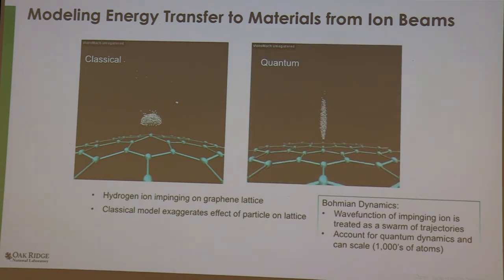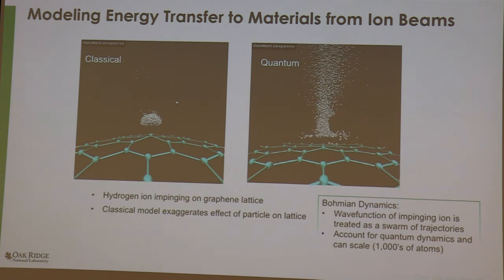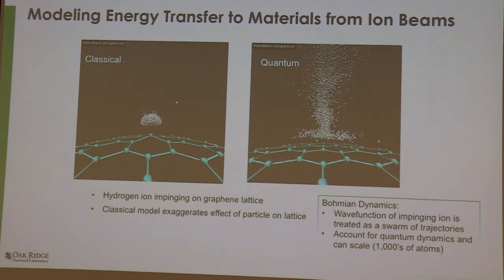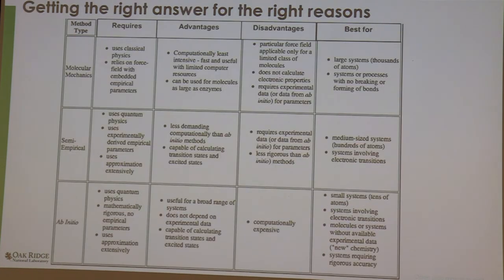And, well, there's a big difference. There's no sticking. Excitation is even different. Quite a different phenomenon, it turns out. There's a little bit of sticking every once in a while, but not compared to the classical. So the classical overestimates everything. The actual interaction leads to sticking, and you could change the potentials, you can tweak with it, and you can get it to look more like this, but it's very complicated. So quantum does become important even in energy regimes where we were hoping it might not be important. So it begs the question, again, back to the point I made before, that you've got to be careful when you apply the techniques, and apply them where they can answer the questions.